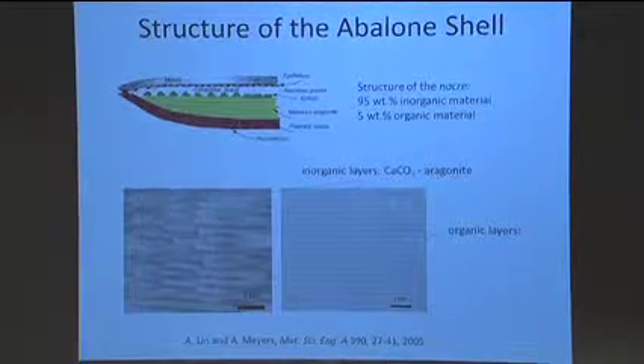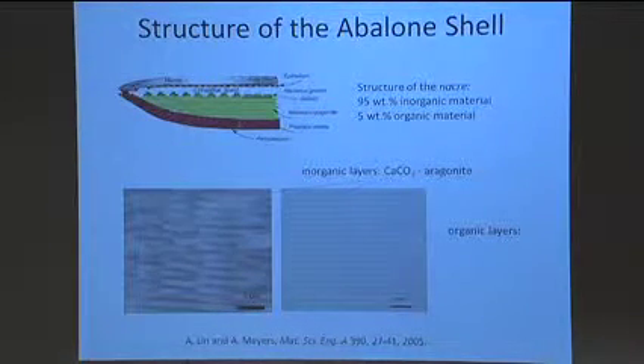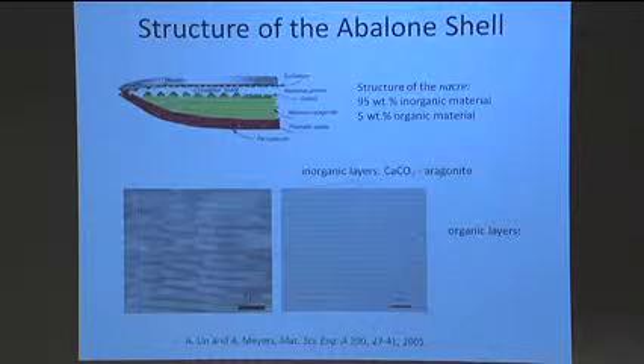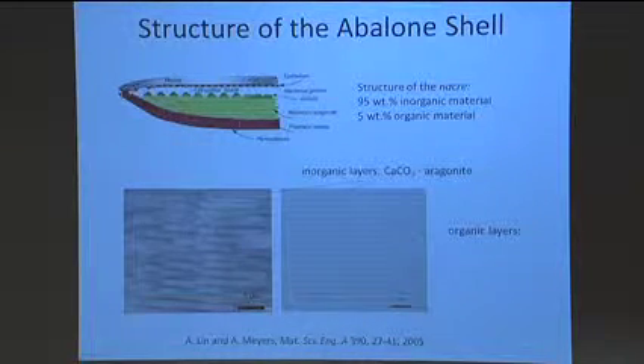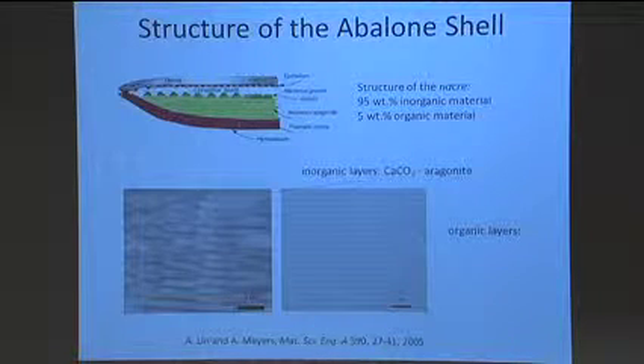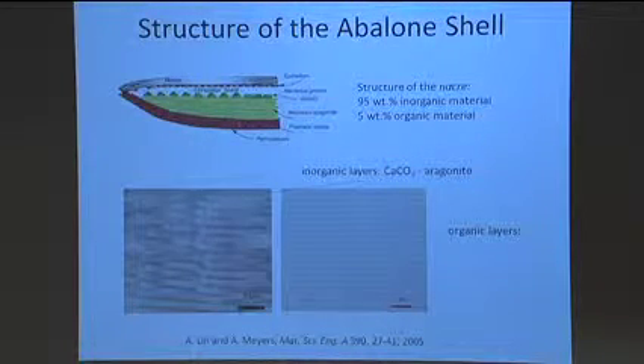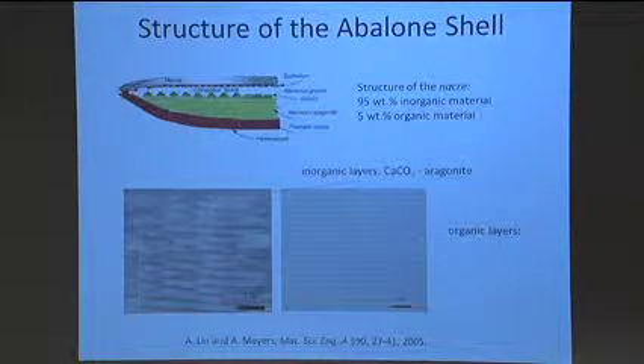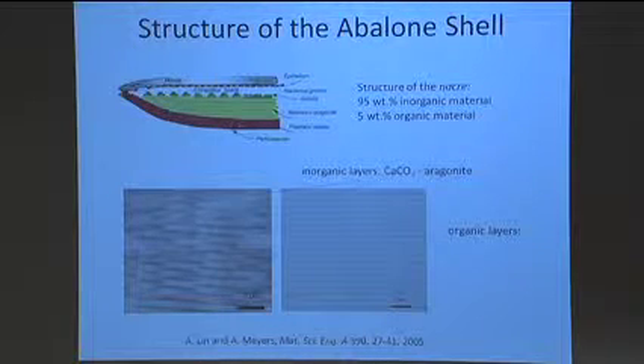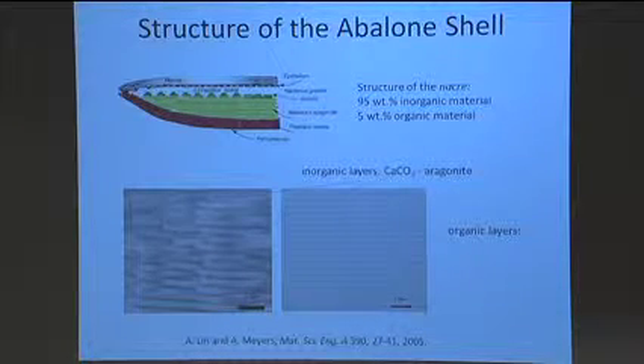If you actually look at the structure, what you find is that this nacre consists of millions of alternating layers of an organic material and an inorganic material. Here, calcium carbonate. The calcium carbonate is about 95 weight%, and the organic material is about 5 weight%. This organic material is essentially a biopolymer. Okay, it's like a hydrocarbon. And what it does is it acts like a scaffold, like a ladder, and it holds these layers together. If you look at the individual components, they're very weak, but in combination and in this structure, it forms a very strong material.